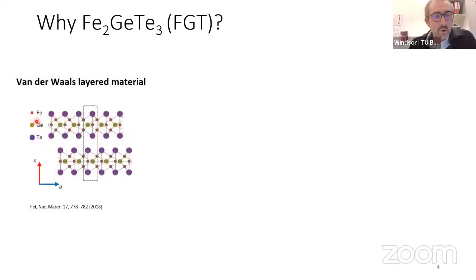Now, why do we want to study FGT in particular, or specifically 2D magnets, as opposed to just 2D materials? Well, 2D materials in general are crystalline in such a way that they can be easily exfoliated and can remain crystalline down to a monolayer limit. And this is a side view of FGT, where you can clearly see that its unit cell, shown here, actually is composed of two different layers. And it's been shown, of course, for graphene initially, but for many other materials afterwards, that it's extremely easy to exfoliate down to a single monolayer and get different electronic functionalities.